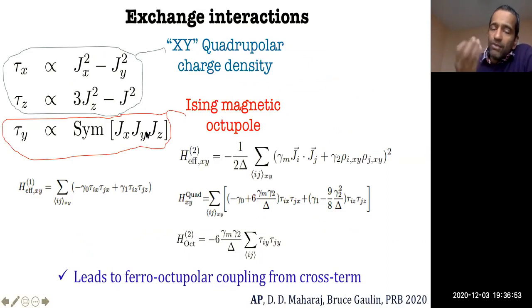Once one does that, you can ask, what is the physics of this low energy doublet? We've understood that there is a low energy doublet in this J equal to 2 magnet. In fact, it's not J equal to 2, it's just a doublet that's important at low energy. And you can ask, physically, what do the Pauli operators that take you between the two states of the doublet correspond to in terms of the microscopic angular momentum degrees of freedom?